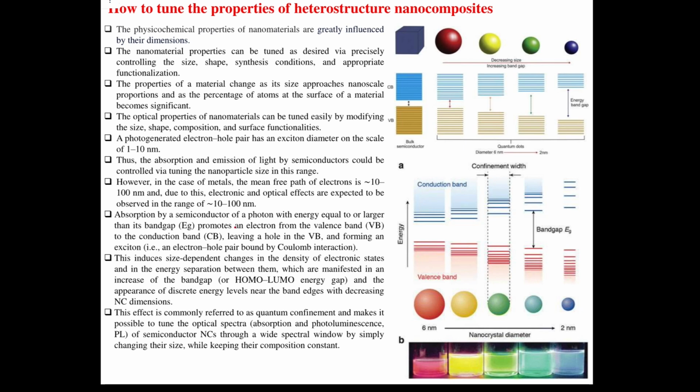So we use impurities, which means doping. We can dope with metals, and we can dope with non-metals. When you incorporate some metal dopants in the TiO2 system, the absorption edge extends into the visible light region of the electromagnetic spectrum, which leads to an energy reduction for the transition of electrons.